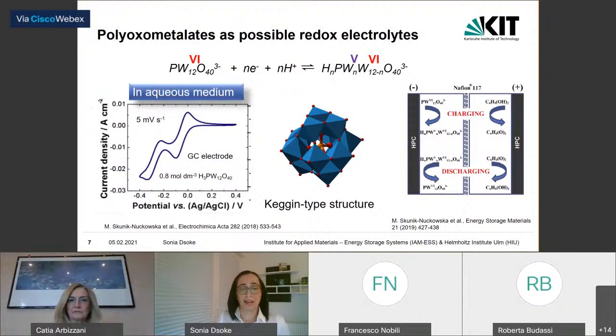And in the context of redox electrolytes, there are different types of species that can be used. And one of the collaborators of Roberto, Pavel Kulesha, together with Magdalena Skunino-Koska, already started to investigate this system by inserting the phosphotungstic acid as a redox electrolyte. And in aqueous solution, you will observe very well-defined multi-step reactions. So the polyoxometalate undergoes multi-step reduction here, with the reduction occurring at the tungsten redox center.